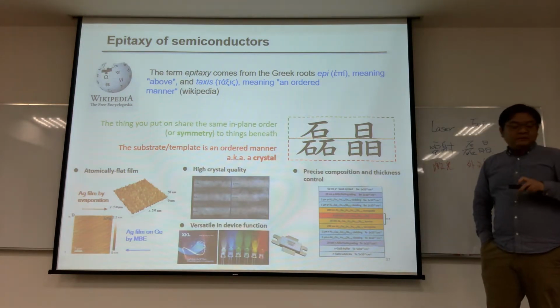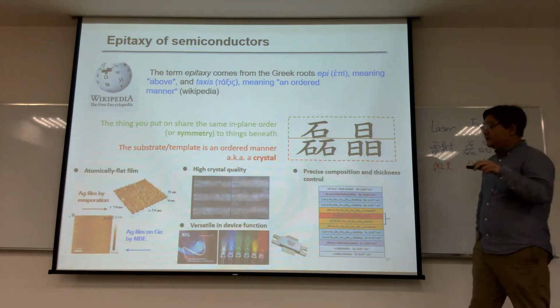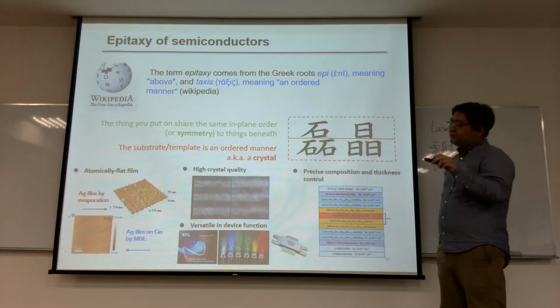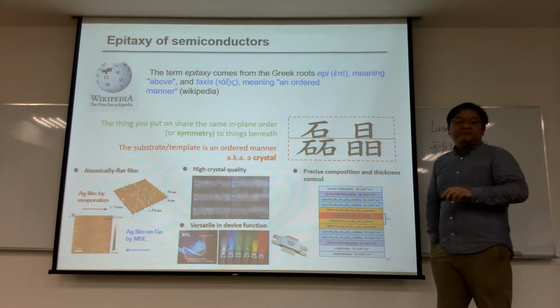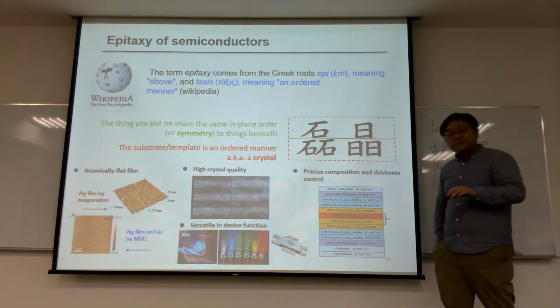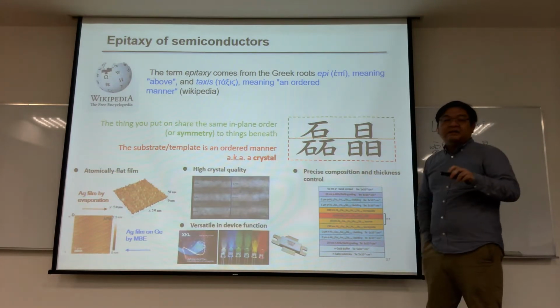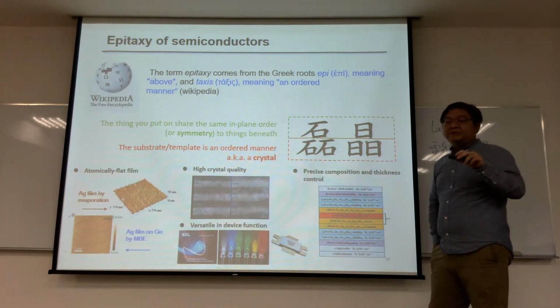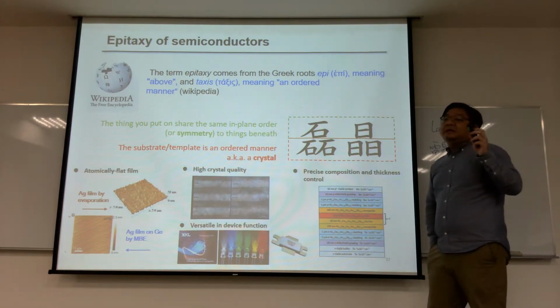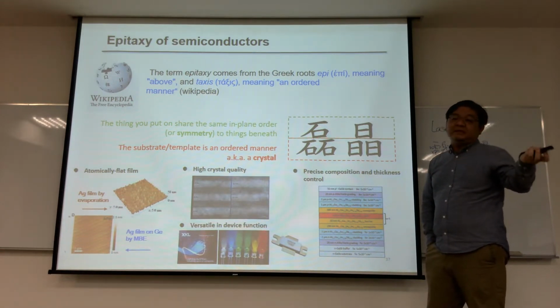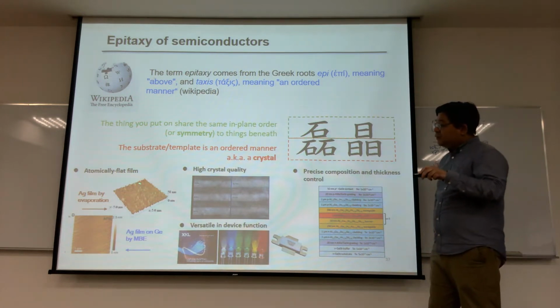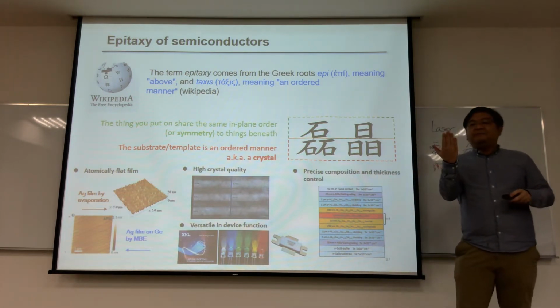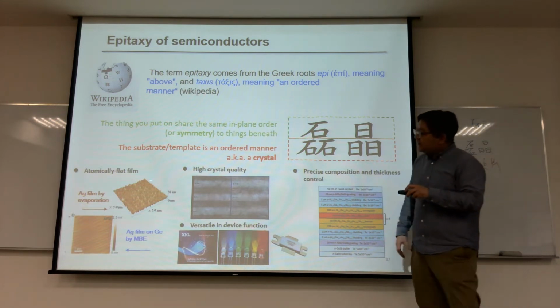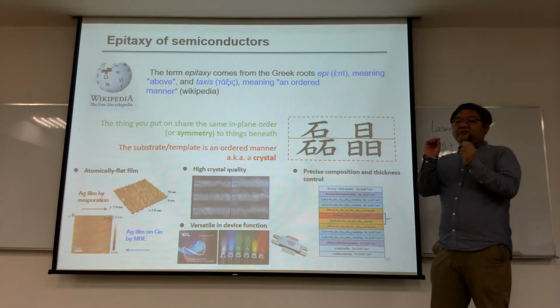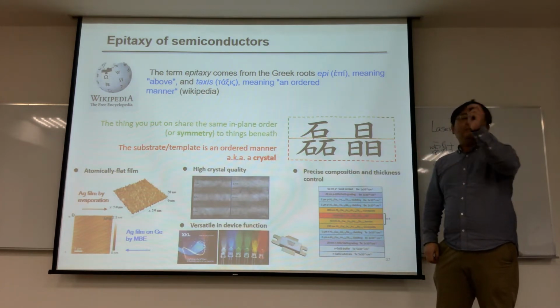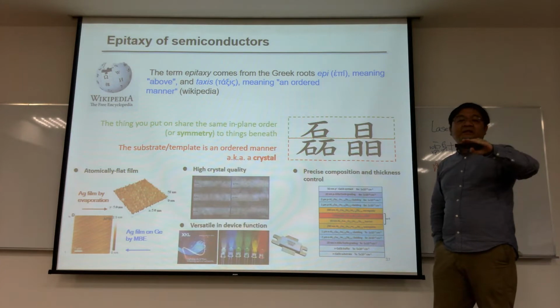So why do we need epitaxy? Epitaxy is important because if you can do epitaxy, you can ensure the things you deposit are also in crystal form. For example, if you deposit a silver film with a common e-beam evaporator, because the growth rate is too fast and the temperature is not high enough, although it looks like a shiny thing and looks pretty good, if you do an AFM scan, you will see it's actually made of very small grains, many at the nanometer level.